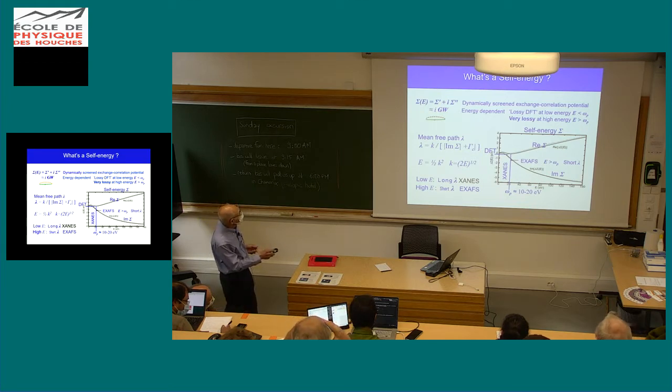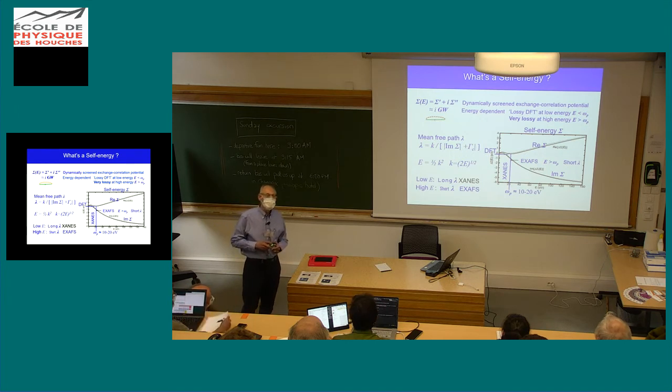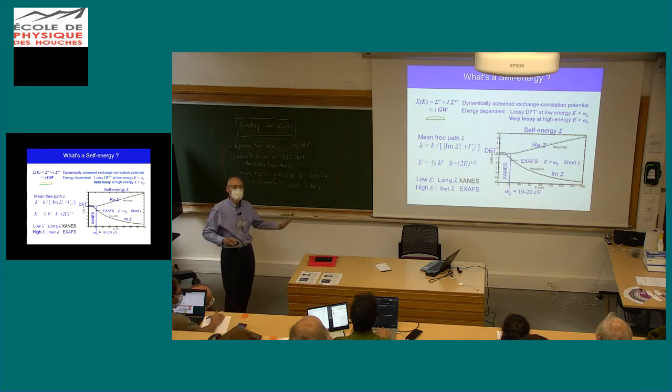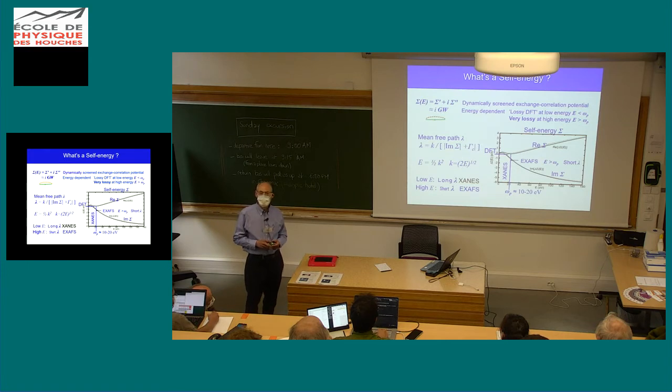The self-energy has a weak imaginary part and very little variation in energy, so you can get away with DFT codes. This is the range where they work great. So first 20 eV, no problems. The problem is that if you really want to do XANES, like what Ben Fado was treating, going out to 200 volts, you're in trouble.